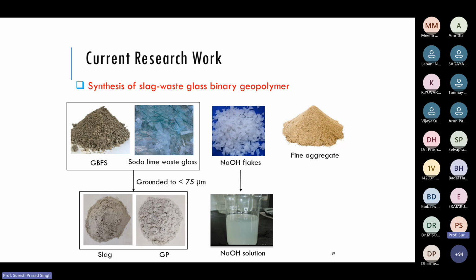Recently we have tried granulated blast furnace slag with soda lime glass. I told you there is a huge amount of waste glass dumped or thrown. The motive of using soda lime glass in geopolymer is that we require alkali material. We use sodium hydroxide, potassium hydroxide or silicates as a source of alkaline material. This soda lime glass contains a high percentage of sodium, and if you use a part of the waste glass along with this slag, the consumption of alkali material will be reduced much.